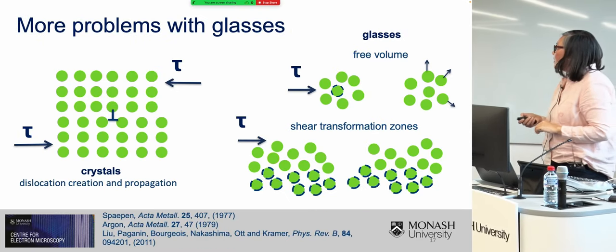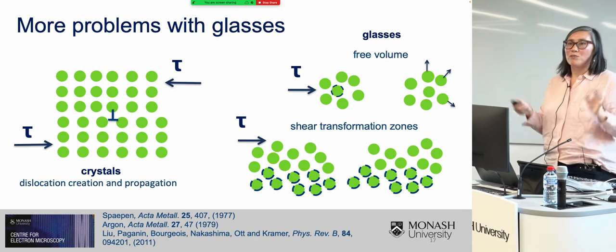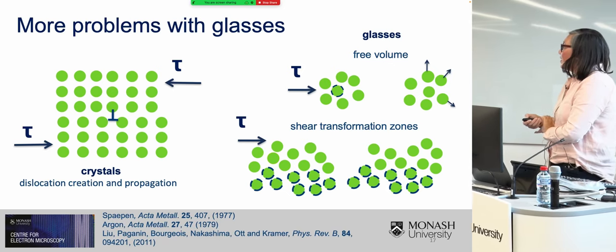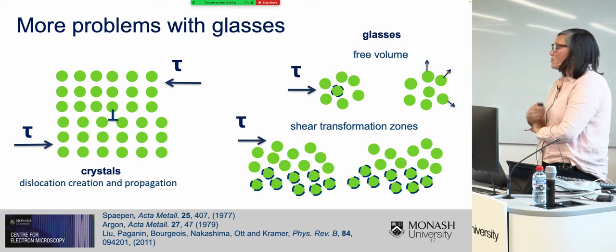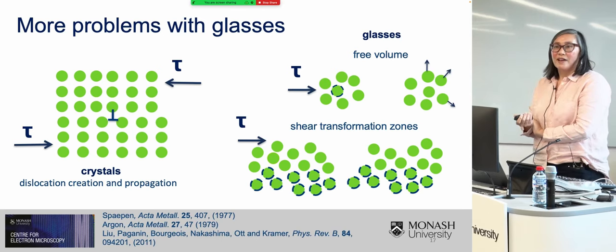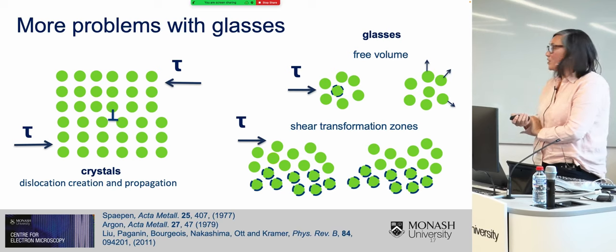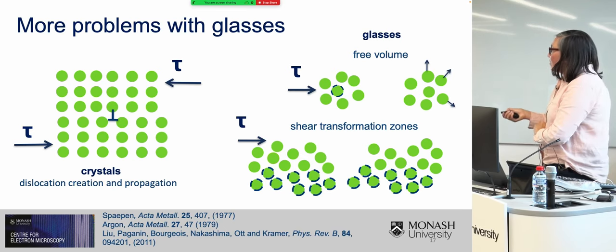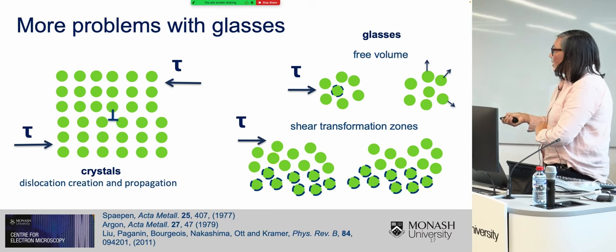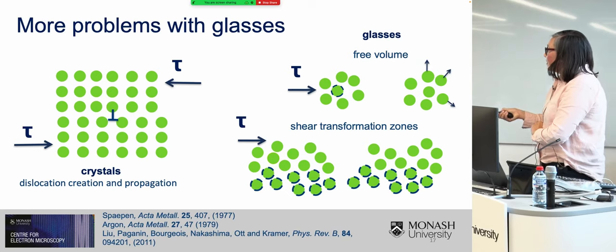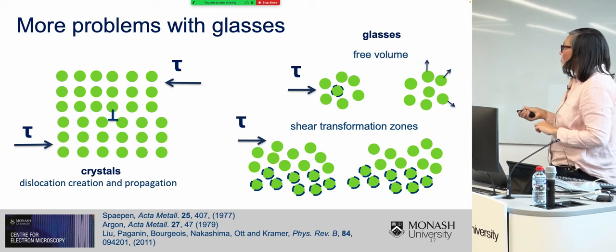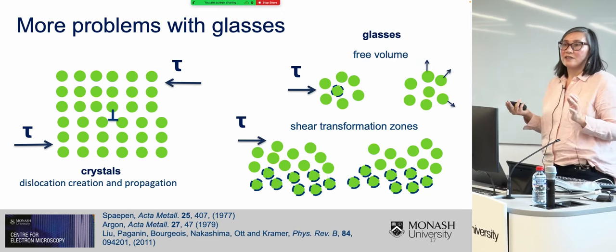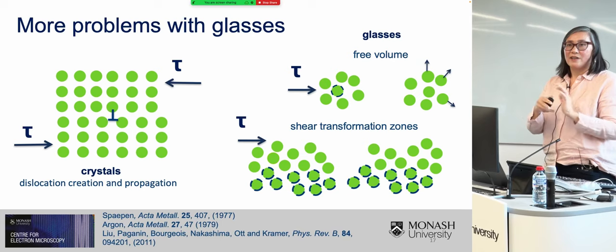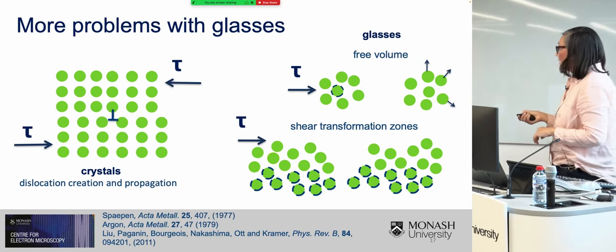Okay, but in the previous slide, I was hinting that there are yet more problems with glasses. And that is that we don't really understand how they deform, and they also suffer from this brittle mechanical failure. So this is a familiar picture of how crystals deform by the creation and propagation of dislocations. In contrast, for glasses, we actually have very little insight into what the structures are that are mediating the deformation.